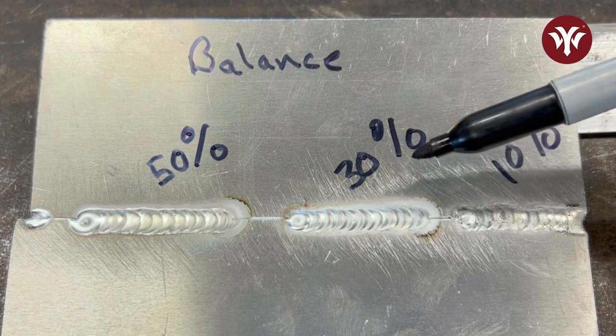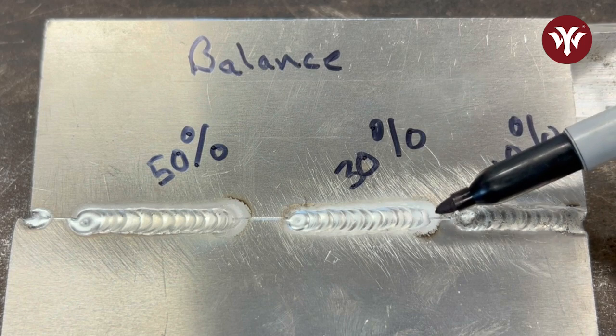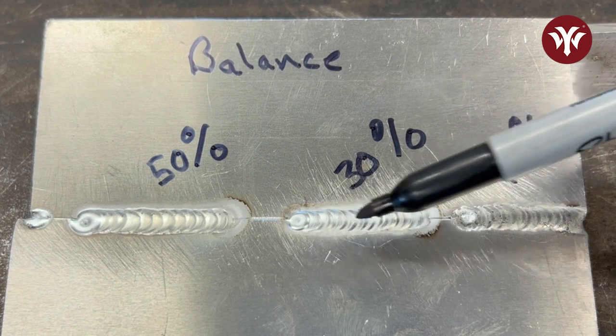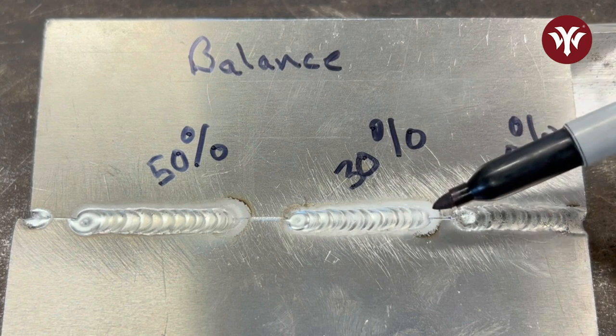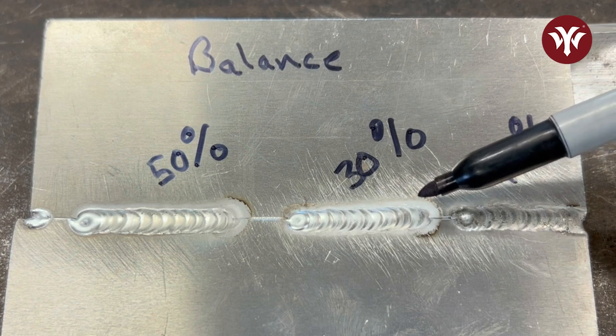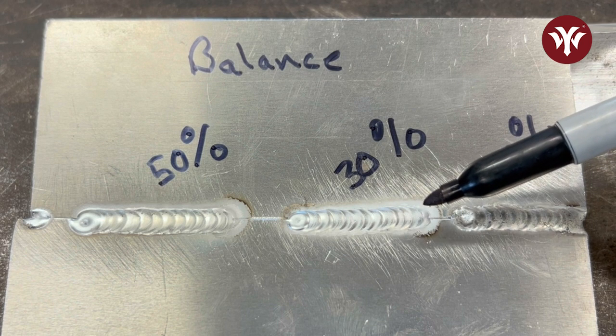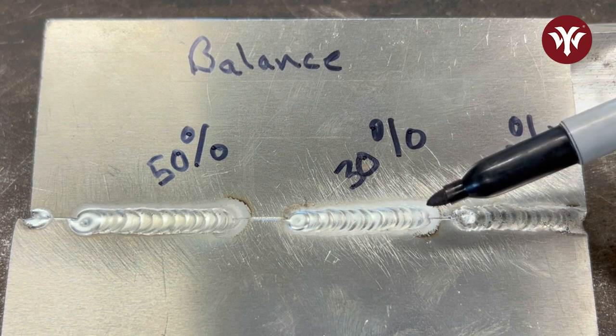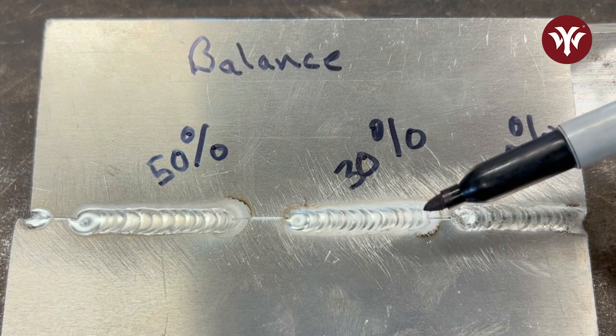30%, as you can see, there's a bit of a difference here. You see that white etching zone? That is the cleaning action taking place, and I'm quite happy with that. For what I do, I'm usually not worried about too much cleaning. I'm usually welding to get a good weld, and also make it pretty.